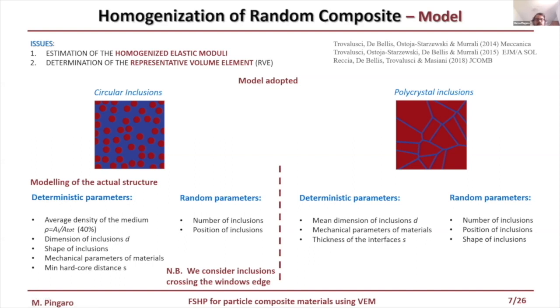Regarding the first assumption, the deterministic parameters are the average density of the medium, the dimension and the shape of the inclusion, in this case circular inclusion, the mechanical parameters, and the minimum distance between the inclusions, that in general in literature is called the hard-core distance. The random parameters are the number of inclusions and the position of the inclusions. I underline that it is very important to consider the crossing of the inclusions on the window edges, because it has been shown that not taking this into account invalidates the results that will be achieved.